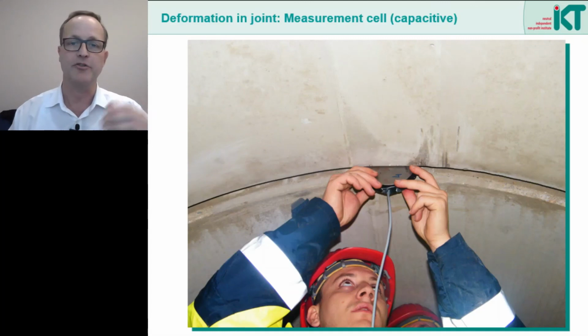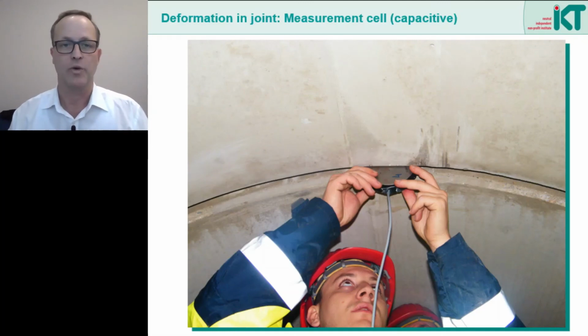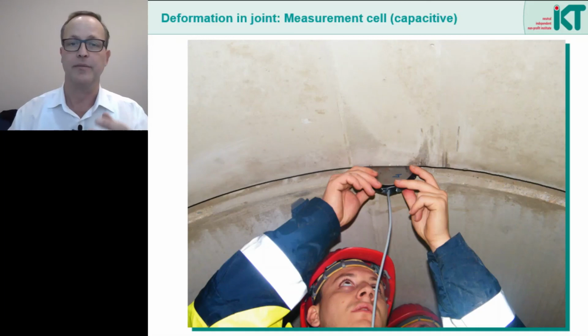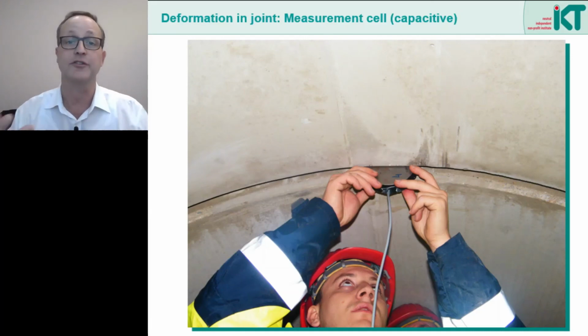Here we see a measuring box for distance measurement, which is pushed into the pipe joint. For this purpose, a small gap was left in the pressure transmission ring before. Here, the measuring box is installed at the crown of the pipe, which is particularly useful for vertical curves, as high stresses can then be expected in this area.